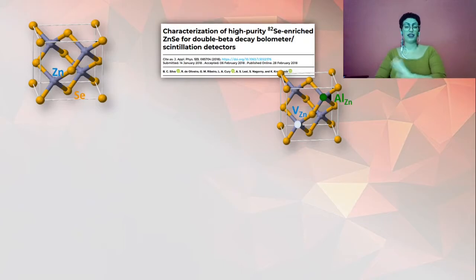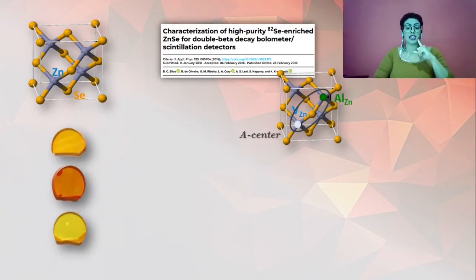The literature explores several types of A centers that can be responsible for luminescence bands in the yellow to red spectral region. However, the conditions under which the material becomes luminescent and the process that leads to it have not been established yet. In this work, we investigated 3 types of ultra-pure polycrystalline non-luminescent samples of zinc selenide grown by the CVD method by the Stanislav group of the Russian Academy of Science. One type of the samples was grown as stoichiometric, named ZnSe, and the other 2 types were grown with excess of selenium or zinc in the composition, named ZnSe-Se and ZnSe-Zn.